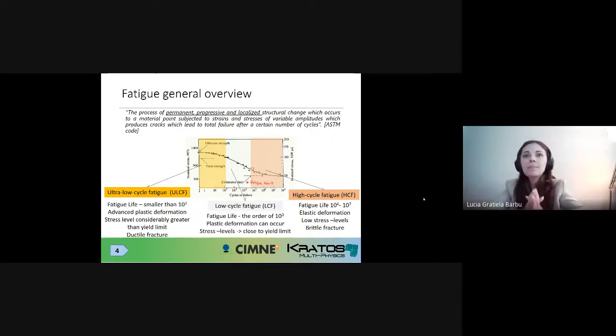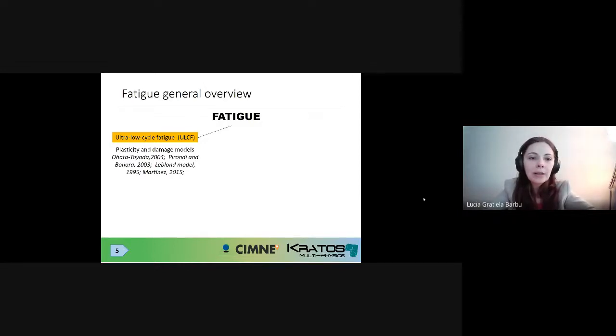Now, in the middle, we have this gray shady area, which I will call low cycle fatigue. The lives are in between the two poles that I mentioned, so let's say thousands of cycles, tens of thousands of cycles, hundreds of thousands of cycles. We can have plastic deformation, of course, at several different levels. The stress levels are close to the yield limit when we are closer to the high cycle domain, and they progressively increase as we get closer to the ultra-low cycle fatigue domain. Okay, now let's see a little bit what the state of the art is. Let's see what the industry does, what the researchers do in each of these types of fatigue.